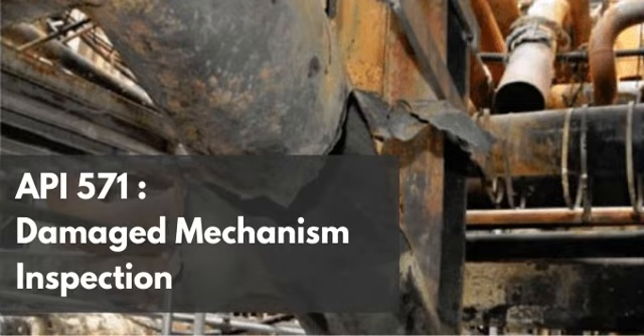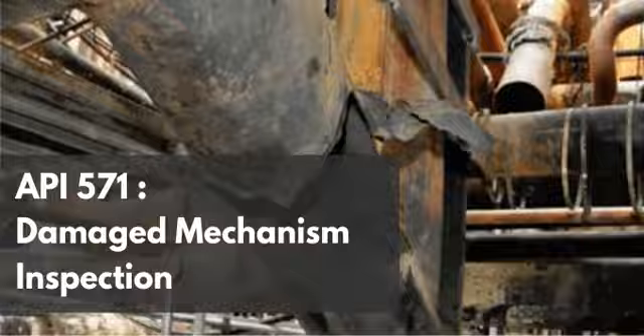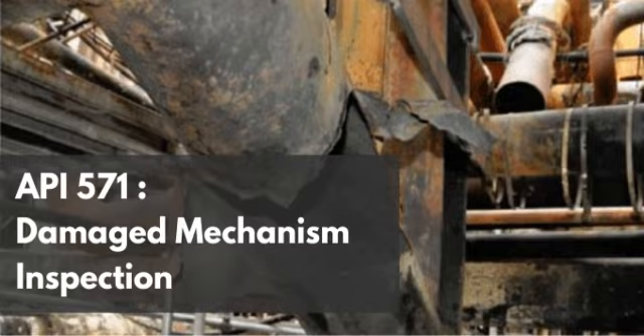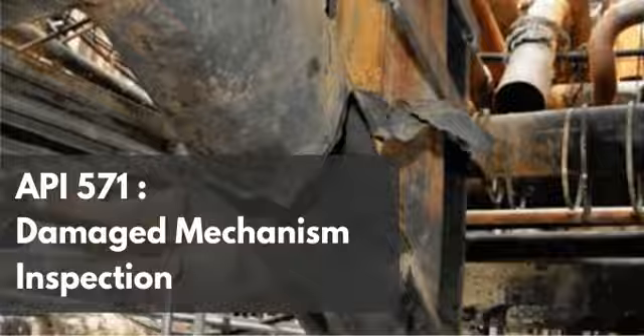It's a great question. Because we are always taught that chromium is the magic element that provides corrosion resistance. I mean, it's the whole reason stainless steel is stainless, right? Yes, and that is the exact logical trap that engineers and sometimes even seasoned metallurgists can fall into when designing these systems. It is a fantastic question. You are entirely correct that in many environments, chromium imparts exceptional corrosion resistance. Right. It does this by reacting with oxygen to form a passive microscopic oxide layer, a shield, basically, on the surface of the metal. However, the operational reality of amine corrosion highlights a critical vulnerability. Both carbon steel and low alloy steels are highly susceptible to uniform and localized thinning in this specific service.